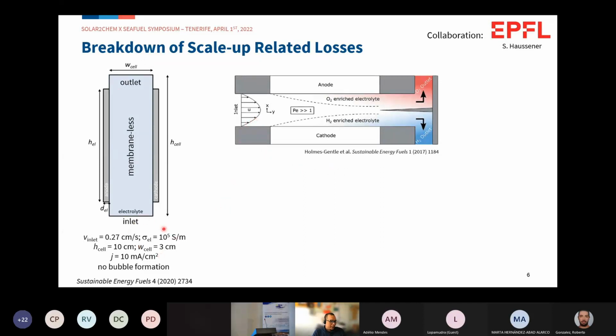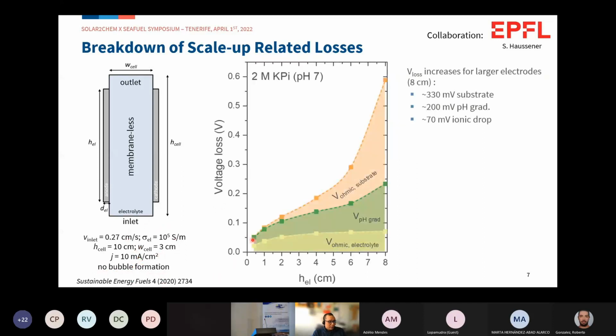The detailed parameters can be found here. We assume no bubble formation, further detailed in the paper. The main conclusion is shown here, where we plot the voltage loss as a function of electrode size. As you can see, the voltage loss increases as we increase the electrode size, and we can distribute that to different contributions: substrate ohmic loss, pH gradient, and electrolyte ohmic loss.